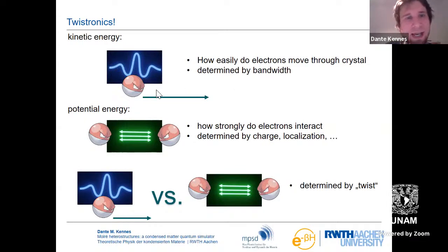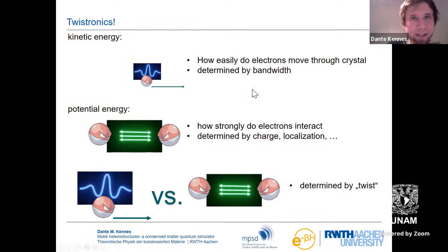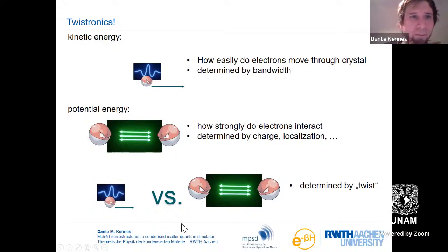So you can think of this twist angle idea as a way of controlling the length scales. And with that, you control the kinetic energy scales. Since you can now go to much larger length scales, you can tune the bandwidth to be much smaller compared to these conventional approaches in solids. So you make the kinetic energy scale of the bandwidth much smaller. That's how easily electrons move through the crystal. But then you also have competing energy scales, such as potential energy scales. For example, electrons interact in these systems among each other. They also interact with the lattice via phonons. And now as you tune these kinetic energy scales to much smaller values, you can actually tune, that is the hope, by this twisting, the competition between kinetic and potential energy scales. So you can hope to tune into a regime where potential energy scales, interactions, are extremely dominant.